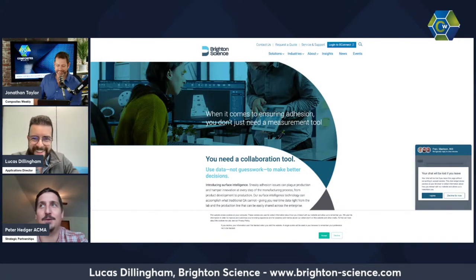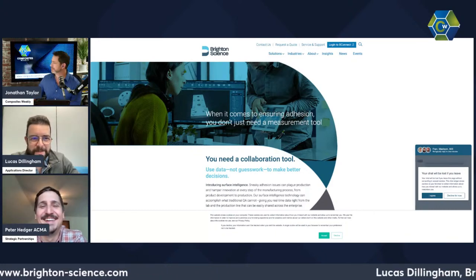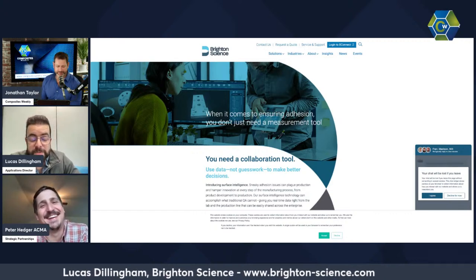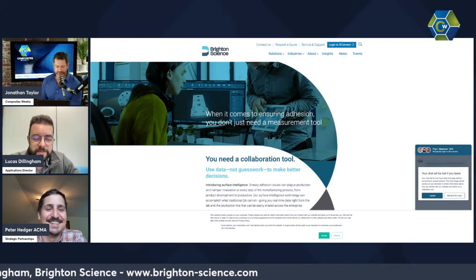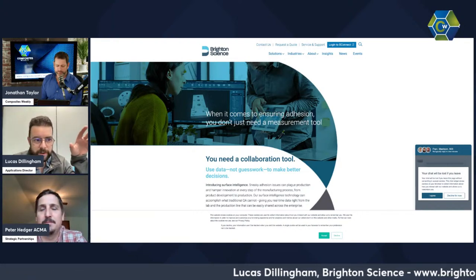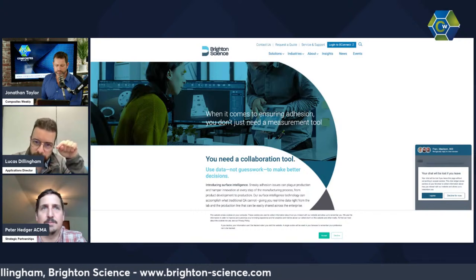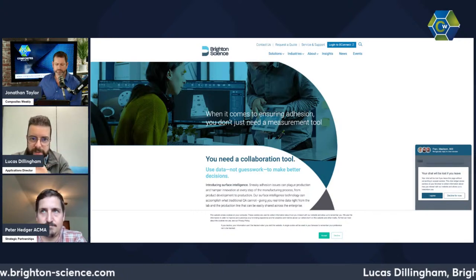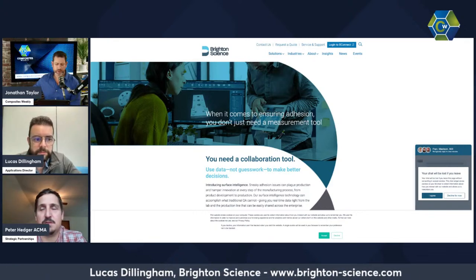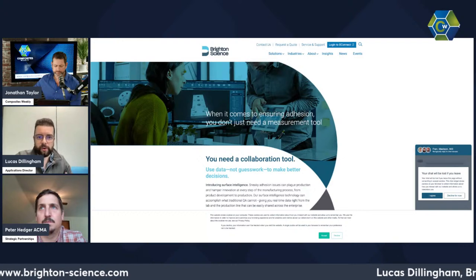XPS is another way. Most guys have an SEM — an electron microscope — and they'll try to use something called EDX, where you put electrons in to get X-rays out. But that goes too deep into the material; it'll tell you what's in the bulk, not what's going on with the surface. That's great for looking at micro-fracturing or cure laminates, but not necessarily for the bonding of the surface. You can't blame guys for trying to use that — it's the tool that's readily available.